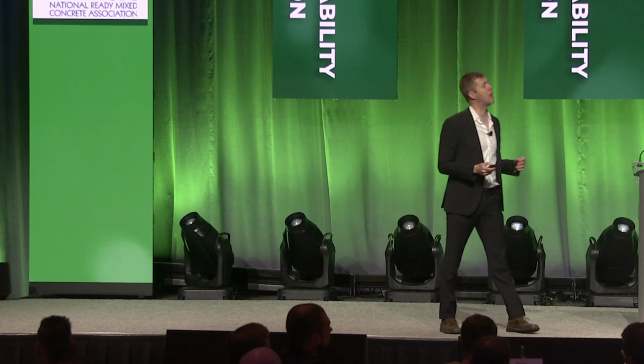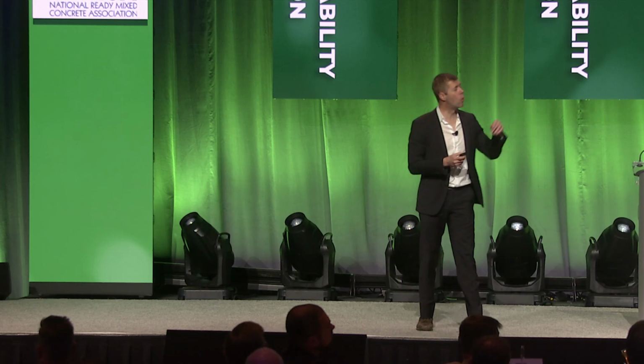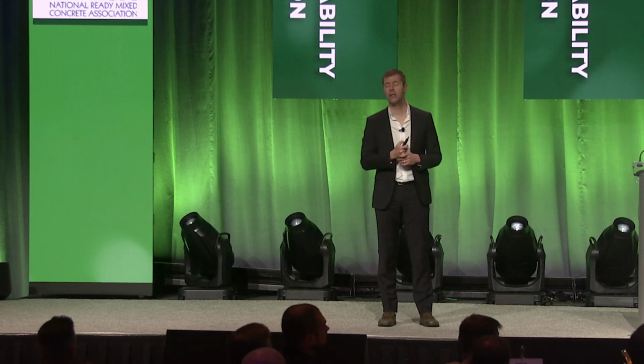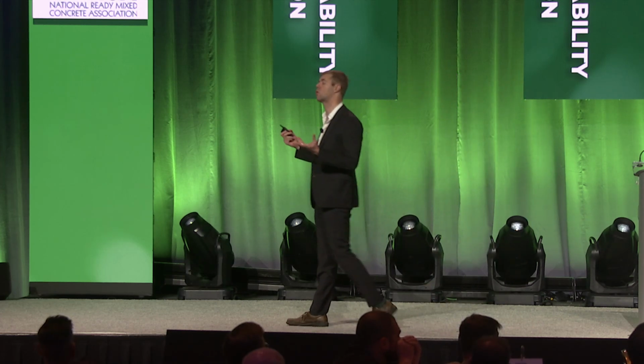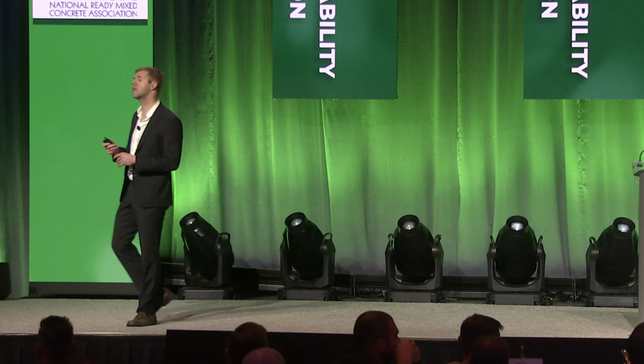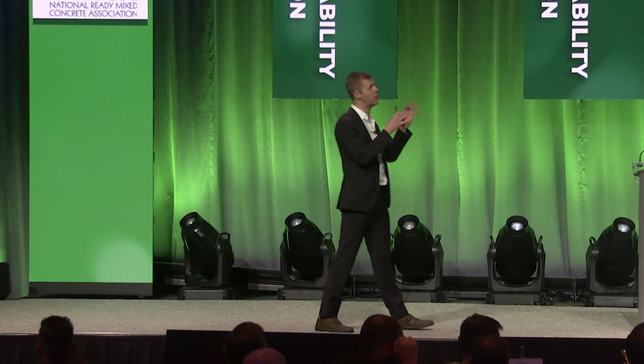And why that matters is that when cement starts to hydrate and grow, I can't see them very well on my screen, but you can see them great on your screens. I got more bonds on the left and less bonds on the right. Okay? More bonds are good. So that means if I go to load this, there'll be more ways for the load to transfer on the left. That's why it's stronger than on the right. Let's say there's outside chemicals that want to penetrate inside the concrete. There it is. On the left, it does a really good job of keeping the outside chemicals out. On the right, it's much easier for them to get inside. This is succinctly why water cement ratio is so important.